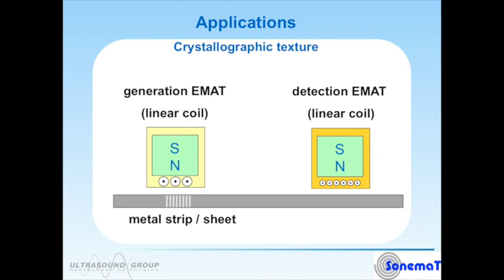The crystallographic texture of a metal sheet is effectively a measure of how random the alignment of the individual grains that form the sheet actually is. Superficially, it does look random, but very small variations can have significant implications for what happens when you try to do something to this sheet that involves plastic deformation. If the rolling conditions of the sheet weren't right, then when you try to plastically deform the sheet, it can result in sheet tearing or sheet deformation in a way that you weren't expecting.